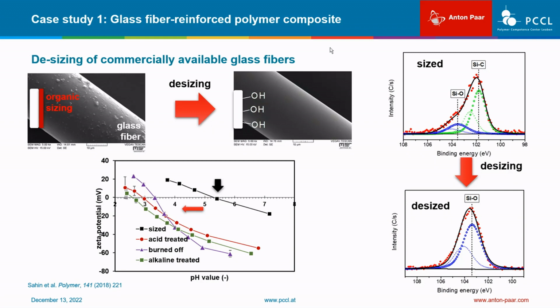Since the desizing step may damage the fiber, the morphology of the fibers after each cleaning step was further studied by scanning electron microscopy. Sized fibers exhibit a rough and inhomogeneous surface that is mainly attributed to the applied organic coating. The surface becomes smoother after the extraction with acetone and the treatment with an acidic piranha solution, which confirms the partial removal of components of the sizing. This result can be confirmed by the isoelectric point of acid-treated samples at pH 3, which differs significantly from the isoelectric point of the sized fiber at pH 5.